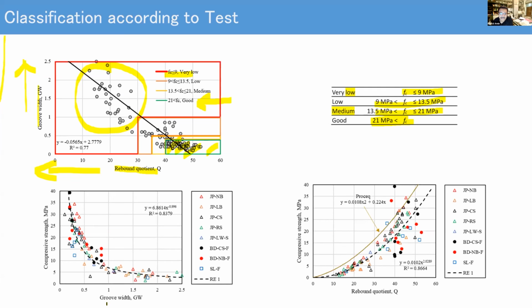Yes, and here we gave you the good correlation we achieved for the groove width and the compressive strength, and here we see there is an inverse relation: the higher the groove width, the lower the compressive strength. Here we determine the groove width for different specimens. These are the field conditions in Bangladesh, and also the Japan laboratory conditions, and so on. And we find this type of correlation. For the rebound coefficient, if we look at the Proceq calibration, it is a little bit away. We used the Proceq hammer in our study, but of course we found our own correlation for the rebound coefficient Q and the compressive strength, as you see in the relation.